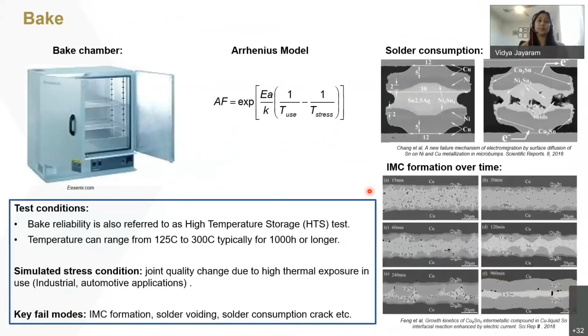The next one is bake. Bake is also called high temperature storage test. How bake differs from temperature cycling or HAST is that it goes to much higher temperatures, almost up to 300 degrees Celsius, and typically for a much extended period of time.